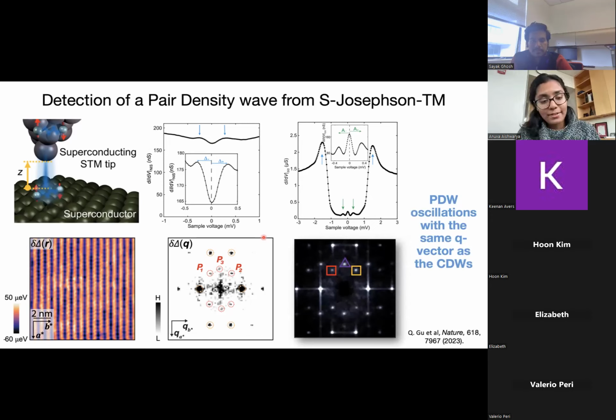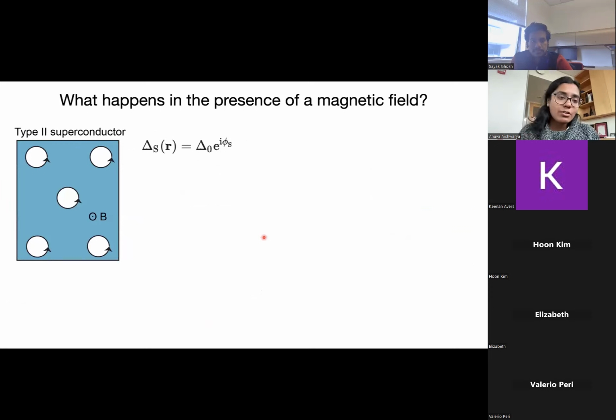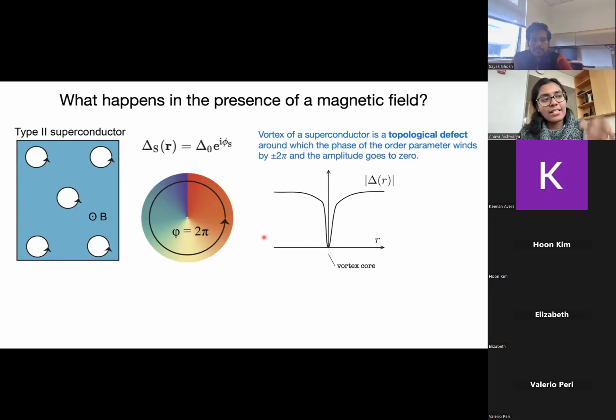we expect to happen in the presence of a magnetic field? So in a usual type 2 superconductor, when we apply a magnetic field, we can punch holes in the superconducting order parameter and have vortices where the order parameter winds by 2 pi. So inside the core of the vortex, the amplitude of the superconducting order parameter goes to 0, and the phase winds by 2 pi around the vortex. So this is like a topological defect.